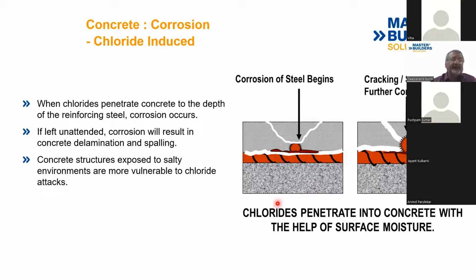Two definite problems in corrosion. The first is corrosion that is chloride induced. This is where the chlorides penetrate into the depth of the reinforcing steel and react with the steel. So the Cl that is there reacts with the Fe to form ferric chlorides, ferrous oxides. O2 will come from H2O, and then there is expansion of the steel bar, and this expansion of the steel bar is going to push the concrete with stress, and that's where your concrete falls. So mostly these are chloride-penetrated corrosions.